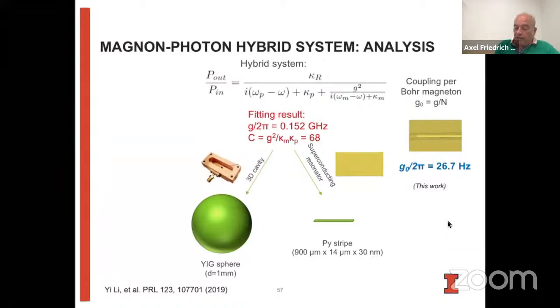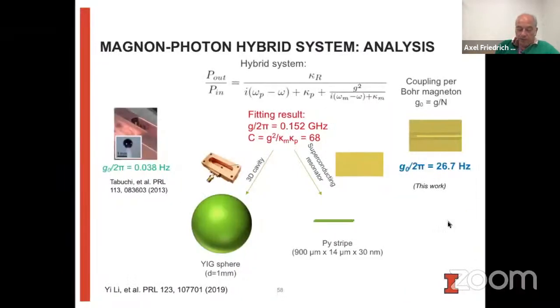So we can now also calculate what is the coupling per individual spin in our system, because we know that the coupling per spin should be given by the overall coupling divided by the number of spins in our system. And if we do this for our permalloy stripe, we get a coupling per spin of about 26.7 hertz. And if we compare this to the YIG sphere, there the coupling per spin is much, much smaller. It's only 0.04 hertz per spin. And the reason is that here we have our magnetic system very nicely situated where the maximum of the photon field is, and the volume is really very well matched to all of this. So that allows us to get much stronger coupling, effectively per spin, in this device structure.